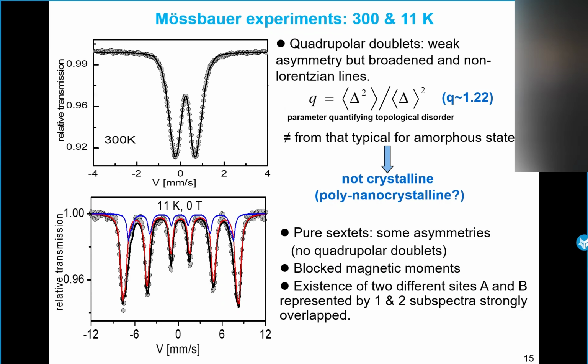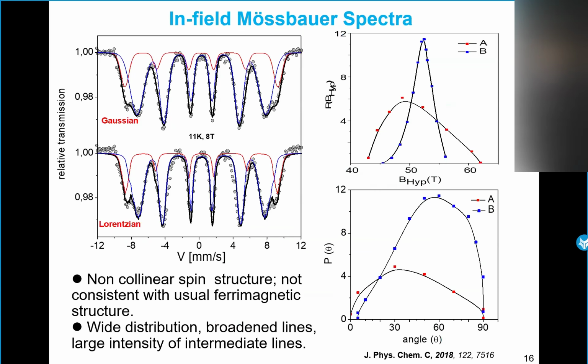So we have something like a polynanocrystalline structure. The measurement without an external field at low temperature shows the presence of a sextet with some broadened lines, very overlapping, and asymmetrical lines corresponding to the presence of A and B sites in these structures. So from that we can't obtain any quantitative information. Now we applied an external field. The obtained spectrum is very complex, not consistent with the usual ferrimagnetic structure as presented previously. The spectrum is characterized by very broad lines for each site, but also large intensity of intermediate lines.